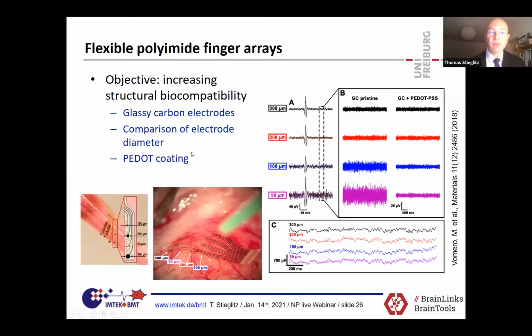We played around a little bit with structures like finger arrays and with glassy carbon as material to investigate if we can use this, not here, but in other investigations to detect, for example, electroactive substances like dopamine, and to see if we can reduce imaging artifacts during MR imaging, having carbon instead of metal as electrode and track material. But I had to cut this out due to time restrictions of that talk. Otherwise, I would have ended up with 150 slides or something like that.